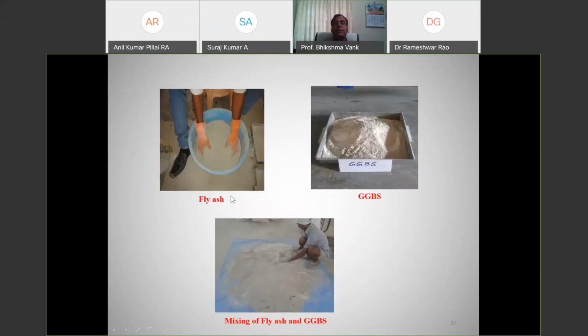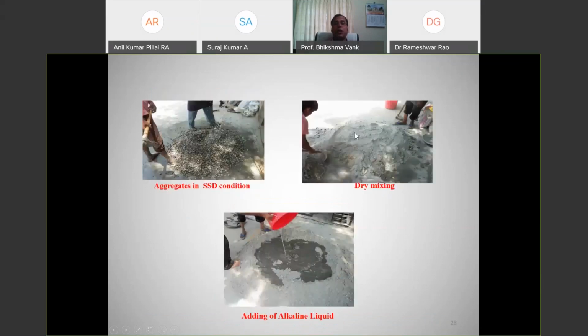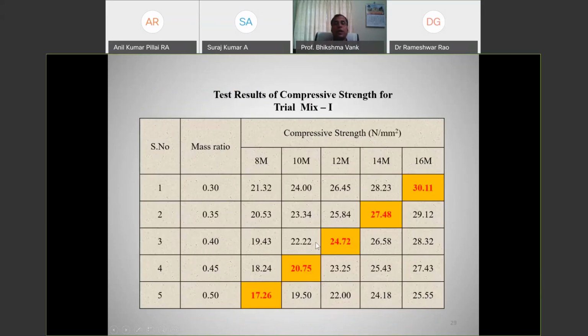And this is fly ash, this is GGBS. This is a mixture of fly ash and GGBS. This is the concrete, how we are making it, as I told you earlier. So the results of compressive strength we got for different molarities like this: 17, 20, 24, 27, 30. As the molarity is increasing, compressive strength is increasing.